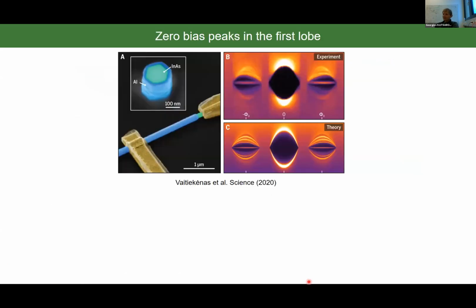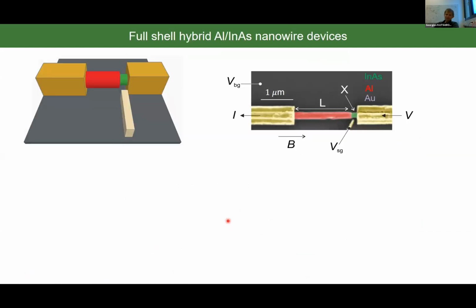This year, the Copenhagen group reported the first measurement on this material system, and indeed they reported a zero bias peak in the first lobe, which was interpreted as a Majorana zero mode. We have done similar experiments. So that's our device: on the right side, you can see the scanning electron microscopy picture, and on the left side, a 3D cartoon. So what you see in green is the indium arsenide nanowire. In red, you can see the aluminum full